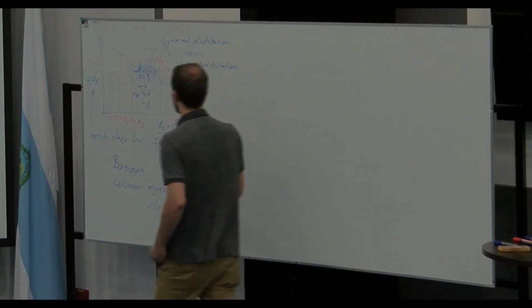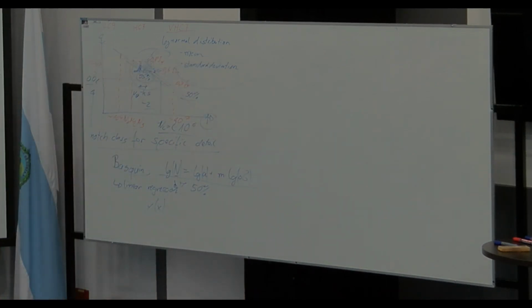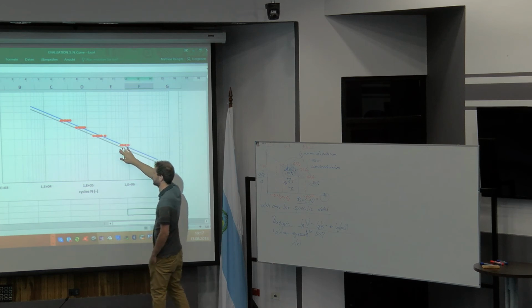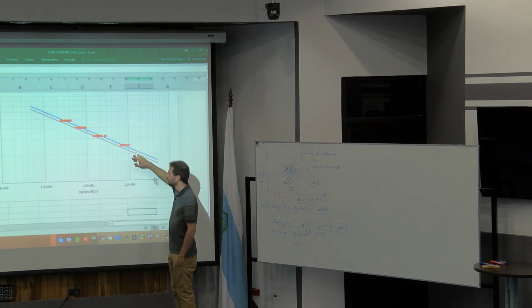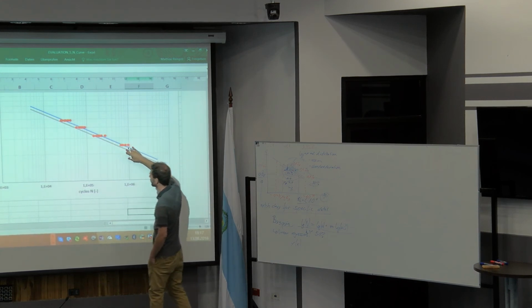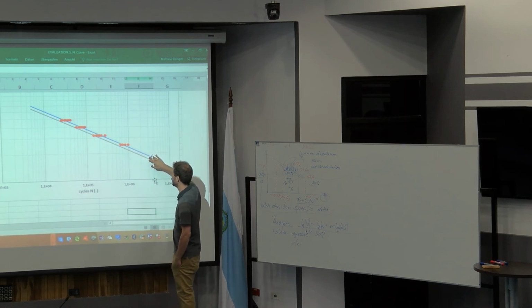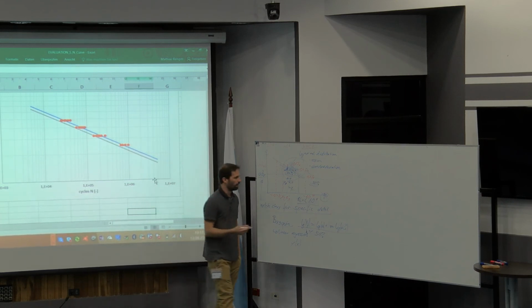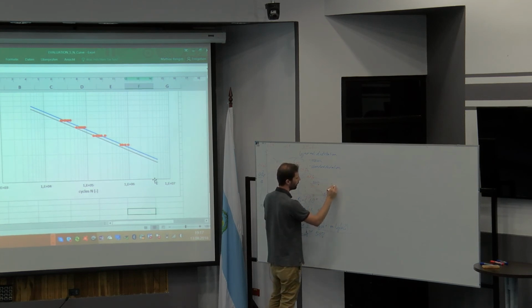But what is going forward? So as you can see here, the tested cycles are here still above the 10 over 6. So if you still decrease the stress range, you get here to a level where you have some tested specimens which are not going here. So at the end, they're going to end up at this level.